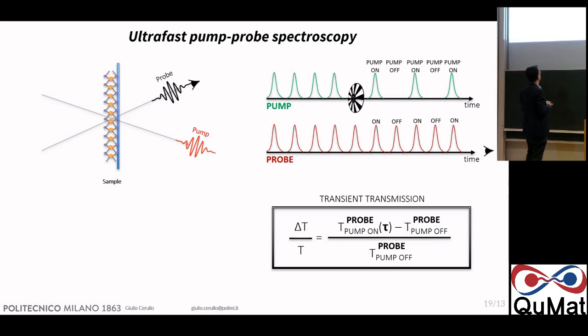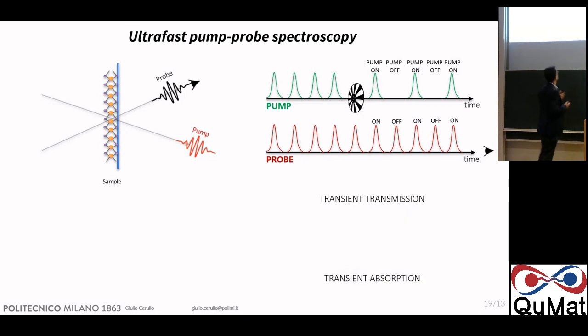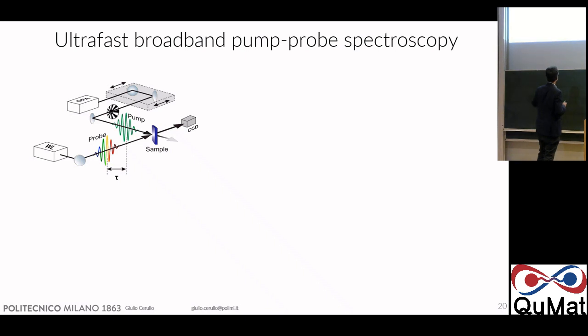Now, how do you do this modulation? Typically, you switch on and off your pump. You have a series of pump and probe pulses, and every second probe pulse, you switch the pump off. And so you measure probe with pump on minus probe with pump off, and you repeat until you get sufficient signal to noise, and then you move to the next delay. So this is how the experiment works.